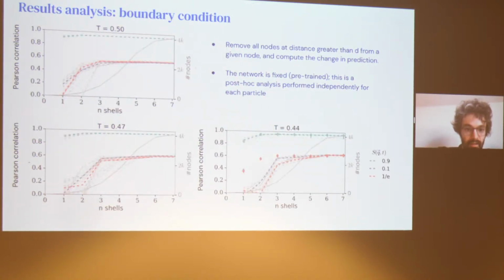What we were seeing is that for the shorter timescales, which are the green curves here, you can remove things up to the nearest neighbor. You can keep only one neighbor shell, and you still get a good prediction. What was interesting is that when you look at larger timescales, the network is actually using these shells further away. So if you remove the first or the second shell, you completely degrade performance, and you recover performance only when you start to include up to 3 shells for a given node. On the bottom right curve, the 3 colors are 3 different timescales. Green is the shortest one, the blue one is the longest one, and the orange one is the alpha timescale, and this is the one that needs the most context.